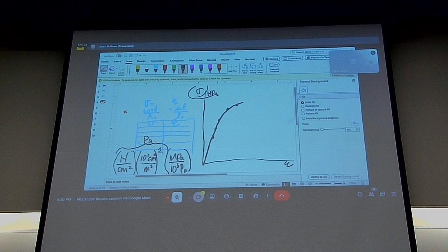And once you have done this, then the maximum value of stress, whatever it is, that's ultimate tensile strength. You can go straight onto this stress-strain graph, look for the point where strain is 0.002, draw a line that's parallel, and wherever it crosses, that is your yield strength.